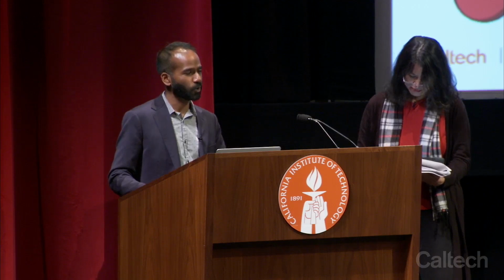One of the remarkable things about Haber-Bosch is that after a century of innovation, that reaction now has a 70% energy efficiency. What we published that I've shown here today is at a 3% energy efficiency. In unpublished work, we're now at above 10%, so we're making progress. But this really does need to get above about 25% in our view to be something that's commercially viable. What gives us motivation, though, is that Haber-Bosch, when it was first commercialized, was at around 10 to 20% energy efficiency. So that's a process that took several decades, and already we're starting to see progress to get above 10%. So we do, of course, want to continue to see that increase, though.